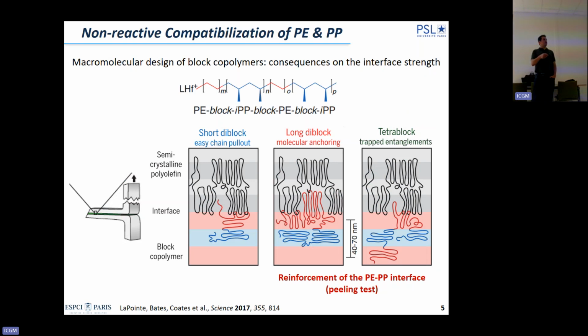And this is very much related to what Jean presented. Not so long ago, there was a very nice publication by the group of Jeff Coates, Frank Bates and Bob Lapointe, where, using a hafnium catalyst, there was in fact a huge development in catalysis, they were able to make multi-block copolymers of PE and PP, isotactic PP, which as you understand now is pretty important. And this was probably the breakthrough: they were able to make multi-blocks, not only diblocks, but also triblocks, pentablocks, and also very long blocks. And they studied the ability of these multi-block copolymers to compatibilize PE and PP and to improve the mechanical properties.